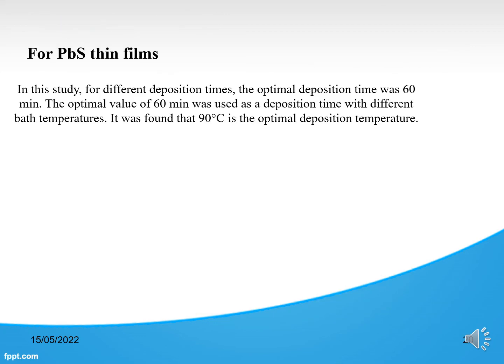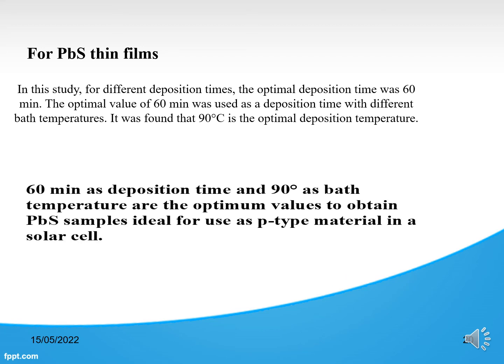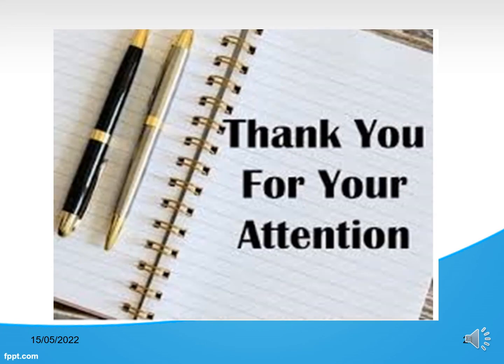For PbS thin films in this study with different deposition times, the optimal deposition time was 60 minutes. The optimal value of 60 minutes was used as the deposition time with different bath temperatures. It was found that 90 degrees Celsius is the optimal deposition temperature. 60 minutes as deposition time and 90 degrees Celsius as bath temperature are the optimum values to obtain PbS samples ideal for use as P-type material in solar cells. Thank you for your attention.